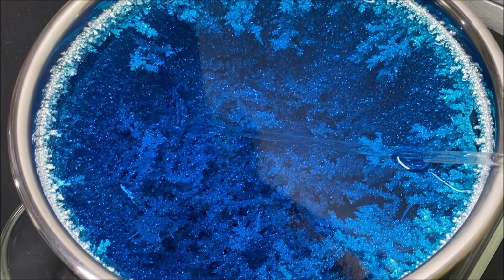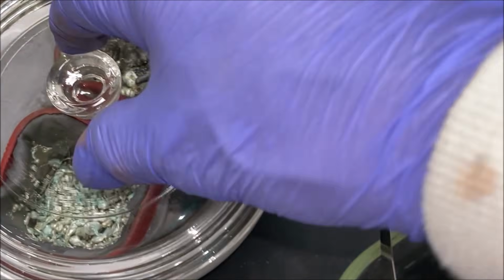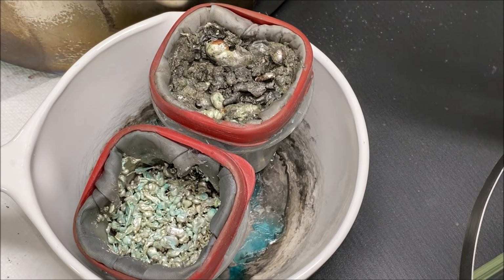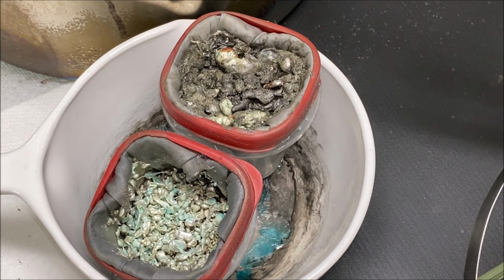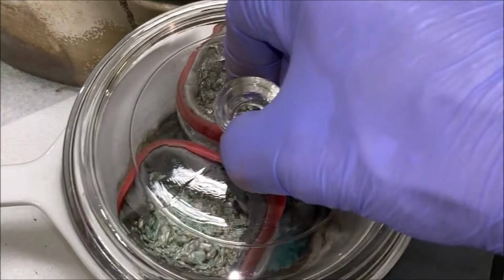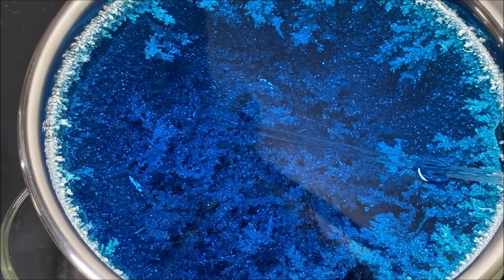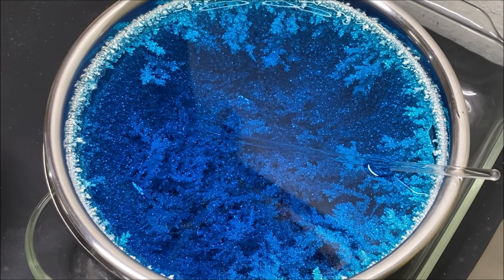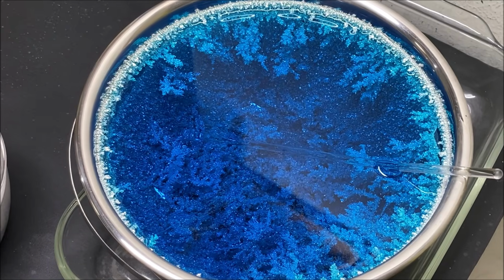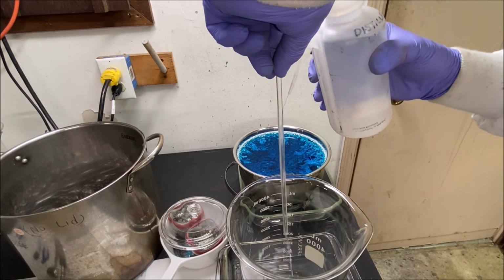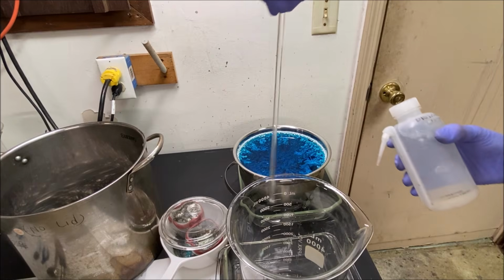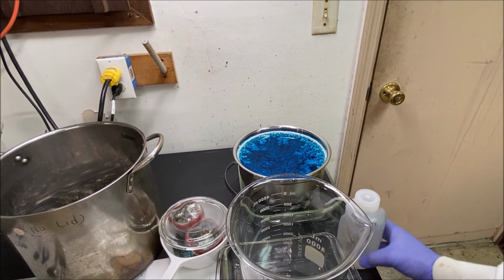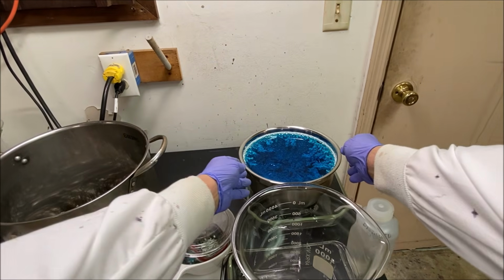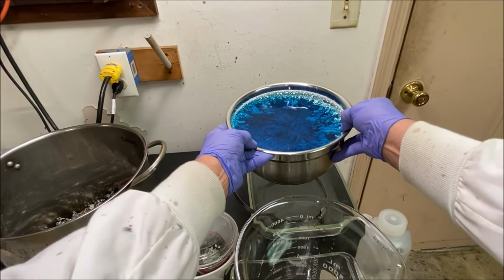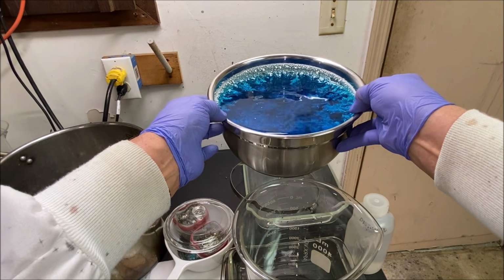The silver ions pass through the filter bag. Any impurities get stuck in here in the filter basket. That will be gold and platinum group metals, and I save those filters and will recover that metal later on. But this is just high purity silver that's been refined electrolytically. I'm not creating silver out of thin air. This electrolyte has been used for 2 runs of the silver cell, and I never use it for more than 2 runs because copper builds up in it. Let's see if we can get this up here. And we're going to dump the electrolyte now into a clean beaker.